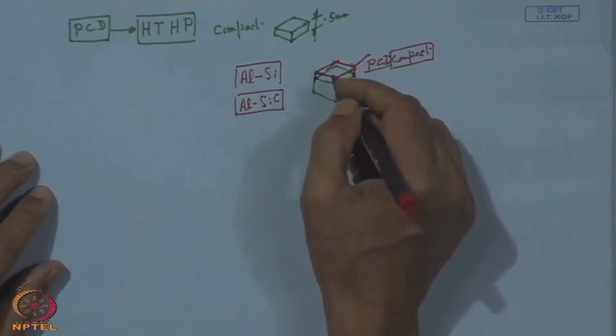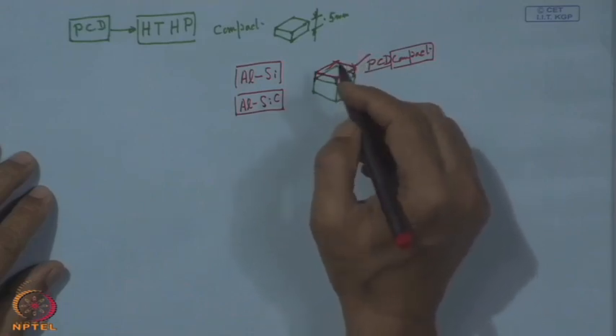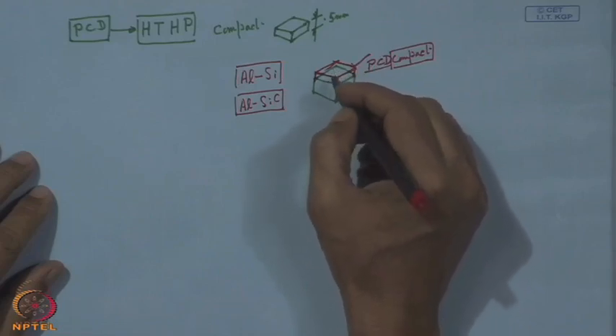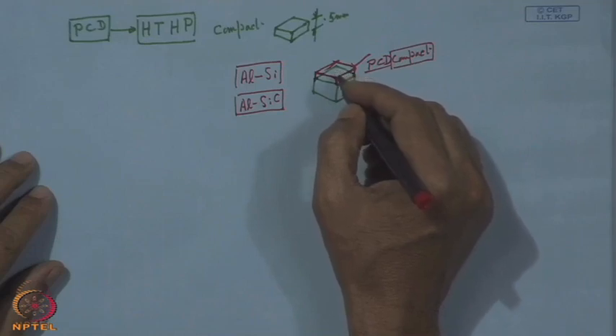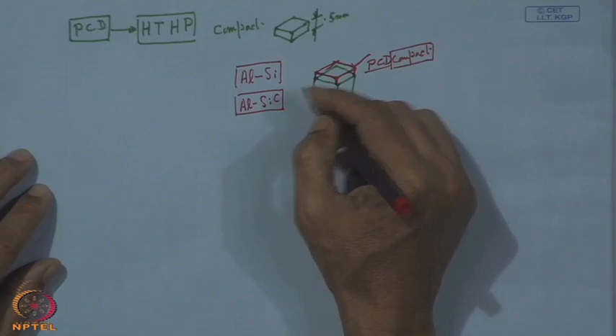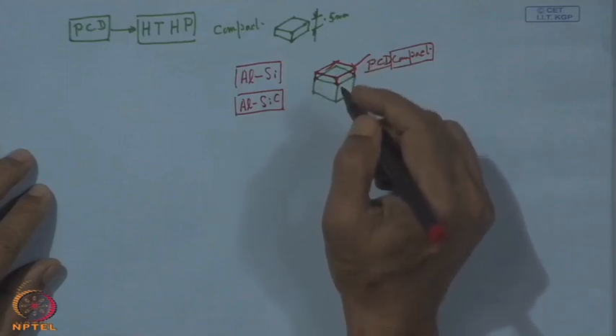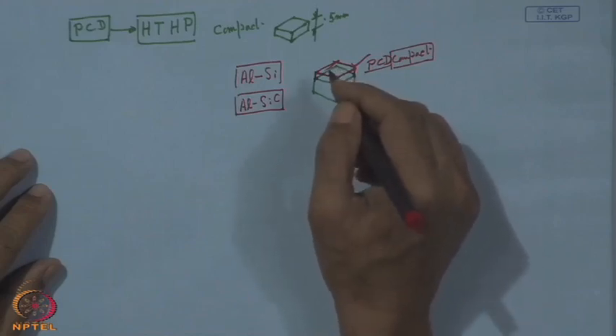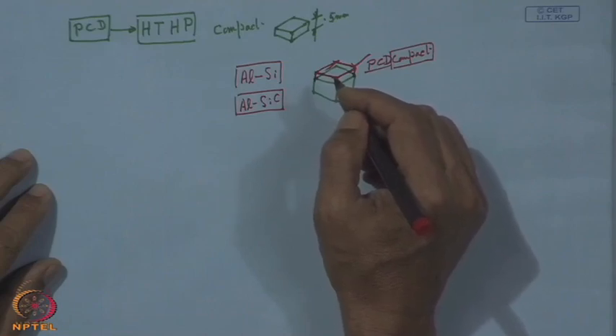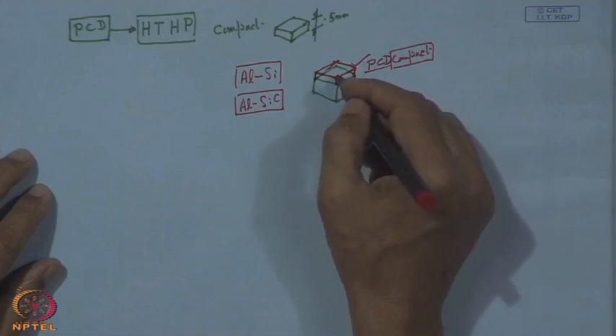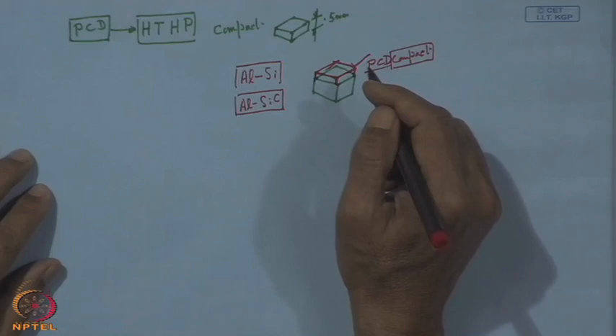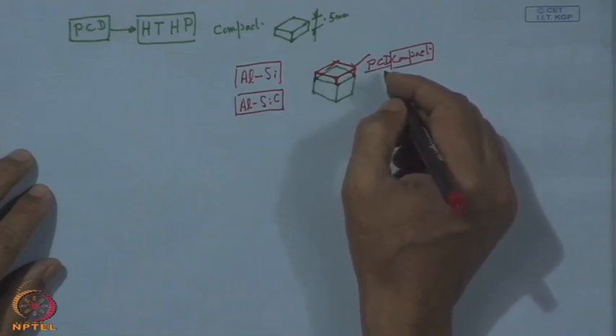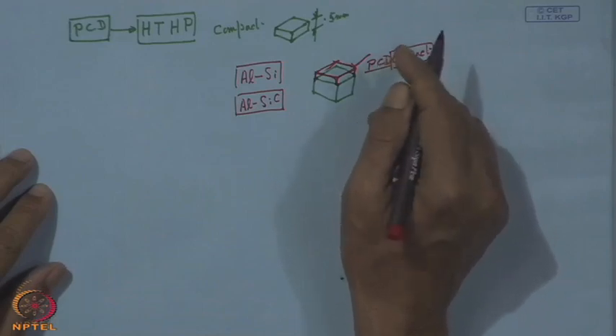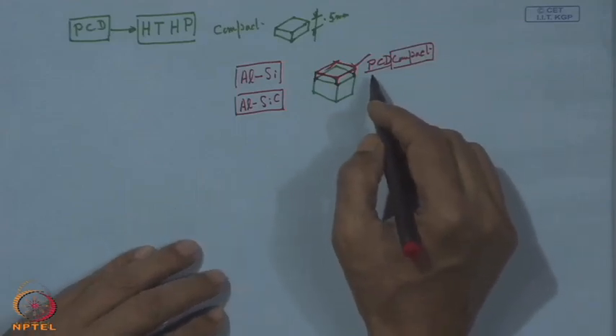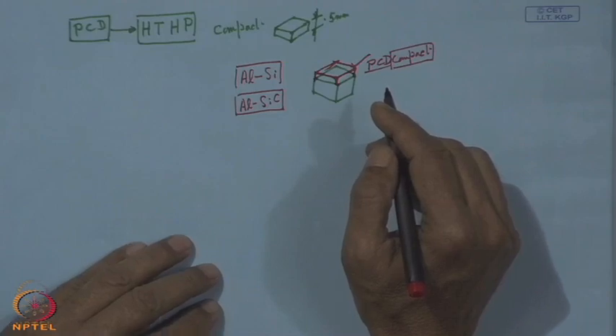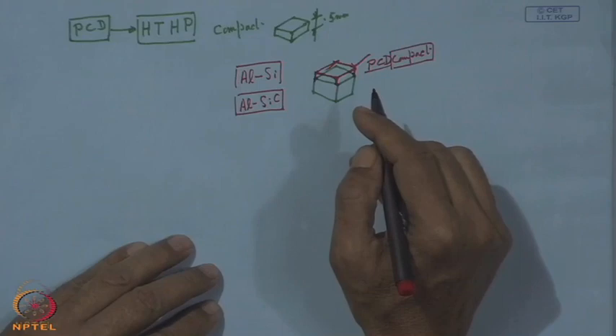However, this is also not free of weakness. The main weakness here is that often cobalt is used for binding this diamond dust or powder, and after this compaction is made, when this tool is ready for use, if this tool is elevated according to the cutting condition to a very high temperature, then there is a risk of conversion of this diamond to graphite in presence of cobalt. So, this is one of the weaknesses of this polycrystalline diamond compact, that means high temperature stability has certain limitation.